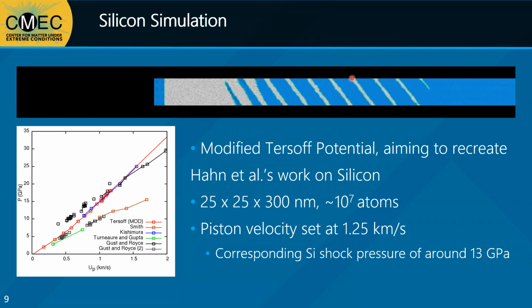Thank you, Farhad. Hey, Alex, Felipe from Berkeley. Regarding the phase diagram in pressure temperature space for silicon, there are several reported phases like DHCP or simple hexagonal, FCC. Did you see any of these phases, or how do your predicted shock Hugoniot points cross this phase diagram? Do they cross at the predicted pressures? For example, the beta tin should appear at around 10 GPa or so.